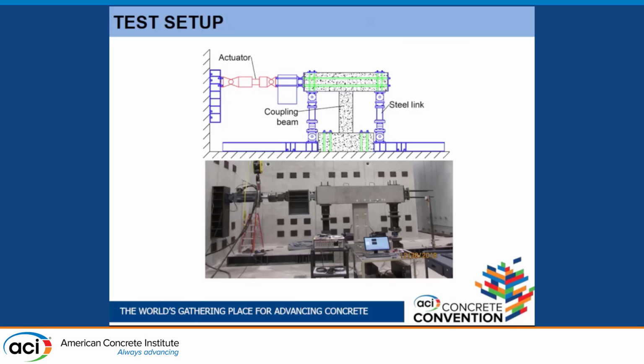The way we tested this, for convenience, we rotated the specimen 90 degrees, so the coupling beam, instead of being horizontal, was vertical, as you can see here. Now, what we wanted to do was make sure the 2 walls being coupled, in this case these 2 horizontal blocks, were fairly parallel, or almost parallel, during the entire loading regime. So we have these steel links that ensure the 2 blocks were basically parallel.